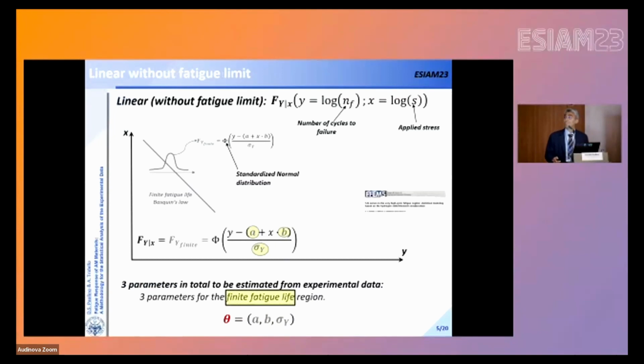Then let's start with the simplest SN trend that is linear without the horizontal plateau, linear without the fatigue limit. In a log-log plot, we have on the axis the logarithm of the number of cycles to failure. This y stands for the logarithm of the number of cycles. And on the ordinate axis, we have x, that is the logarithm of the applied stress. And then we have a linear variation in this bilogarithmic plot.